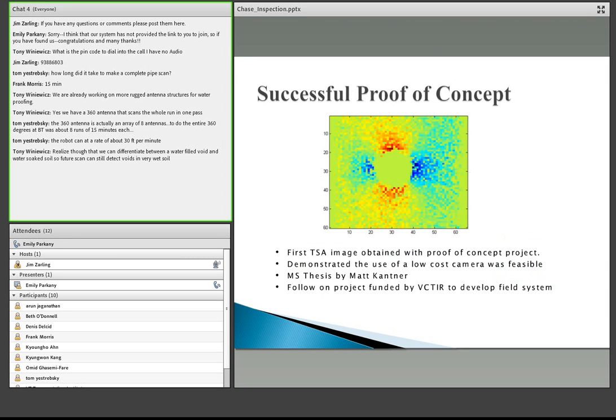The concept is to take infrared images while the specimen is being loaded dynamically, store that information in the computer, and also at the same time collect a reference signal that is correlated with the load that's being applied to the specimen. We then process all of those images that have been collected and only extract out the information in those digital files that is correlated with the loading events that should have produced the thermoelastic signal. So if we're successful, we should end up with an image that looks something like what the theoretical image for a hole in a plate should look like. And this was the image that was produced by the proof of concept test and the low-cost camera at the end of the proof of concept project funded by MAUTC.